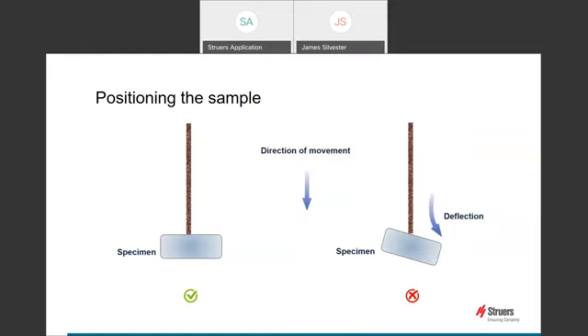Also, if possible, the cutting wheel should approach the sample at 90 degrees. This will help keep the cutting wheel moving in a straight line and give the straightest possible cut. If the sample surface is at an angle, the cutting wheel will deflect slightly. If this happens, the wheel will not be able to straighten up by itself during the cut. If this situation continues, the wheel will cut further and further offline until eventually the wheel fails, or you cut into the cutting bed.